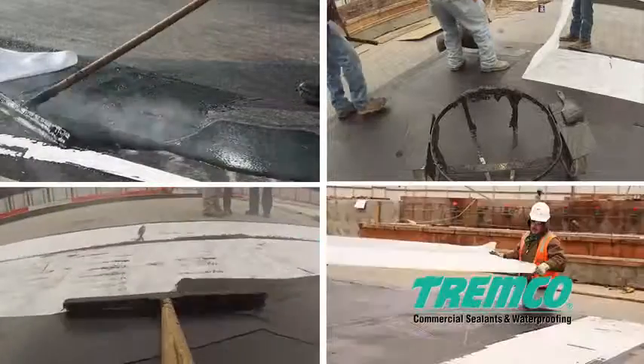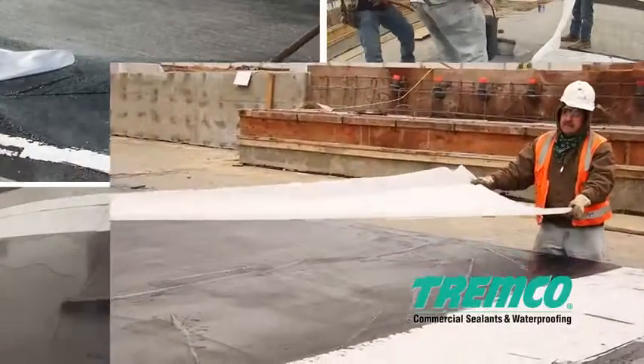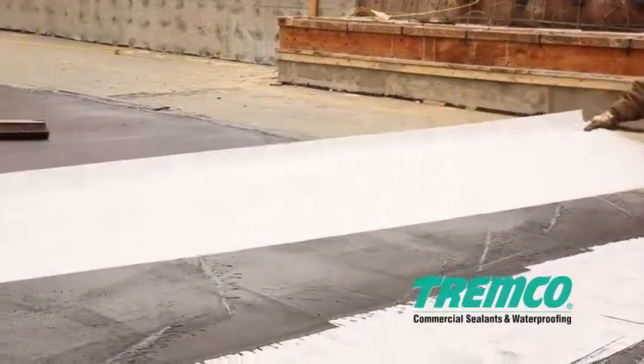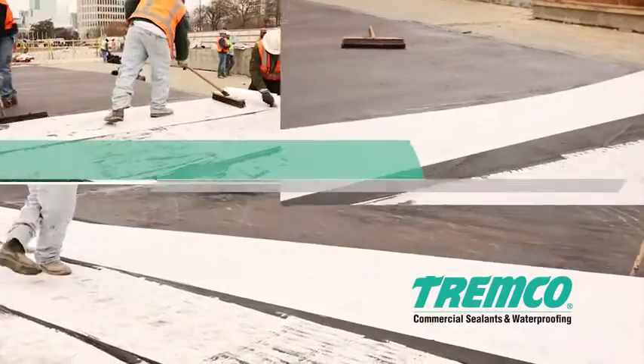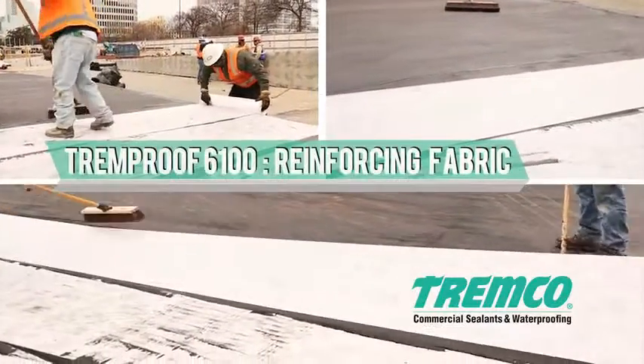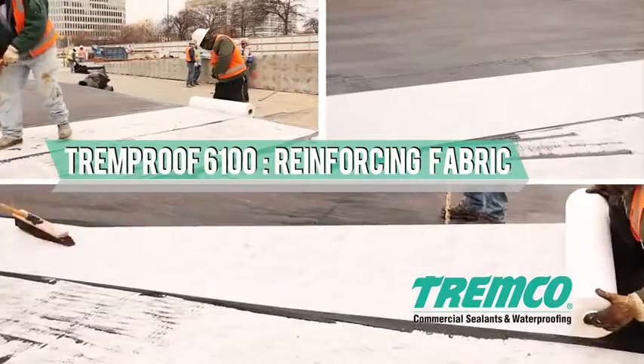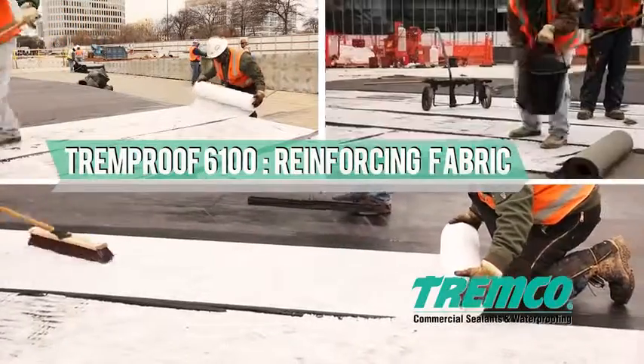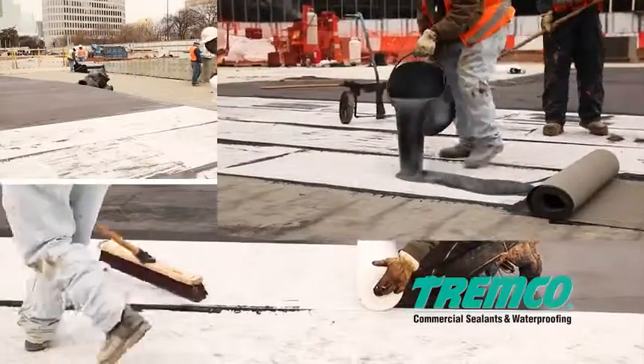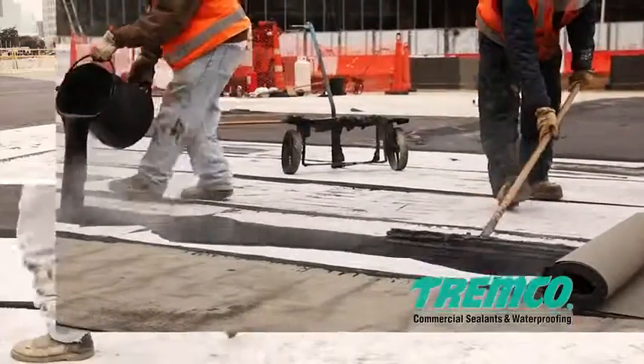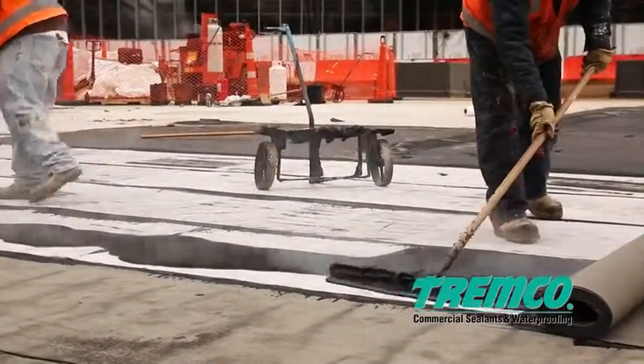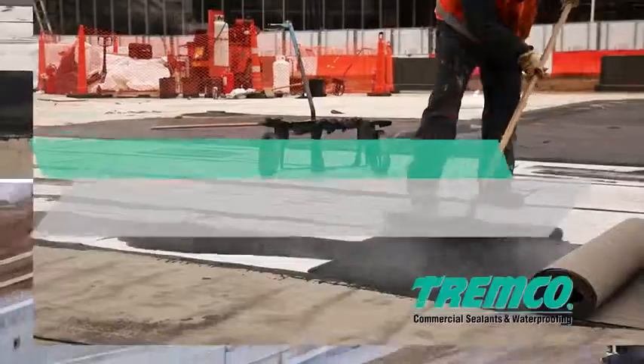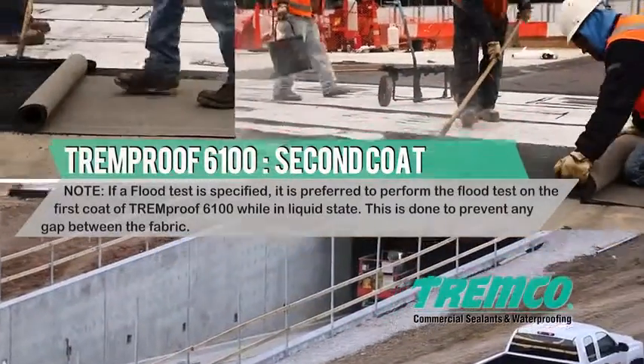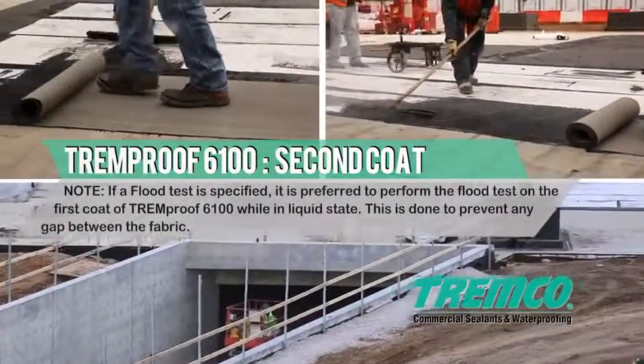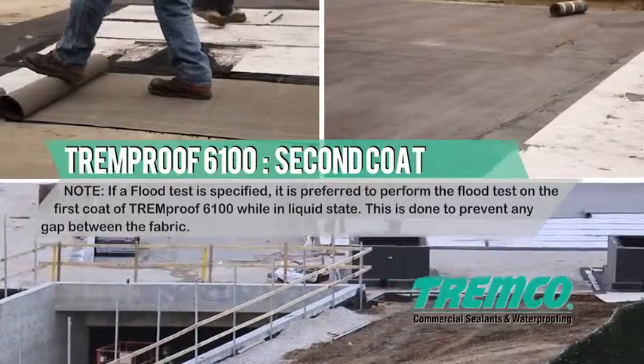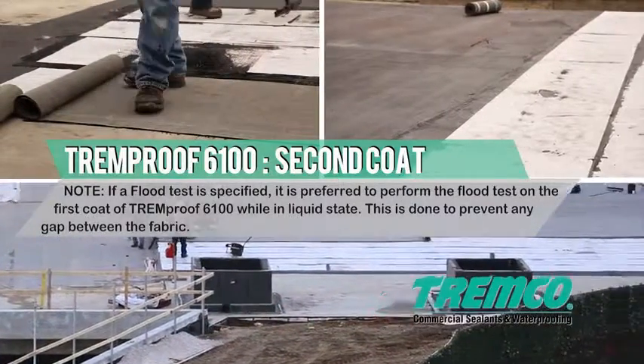TREMproof 6100 Reinforcing Fabric. Immediately install reinforcing fabric with a slight overlap of adjacent sheets into the first coat of TREMproof 6100. This is done to prevent any gap between the fabric. Apply second coat of TREMproof 6100 over the reinforcing fabric at a minimum of 125 mils. Total thickness will equal the documented specification. Nominal thickness will be 215 mils.